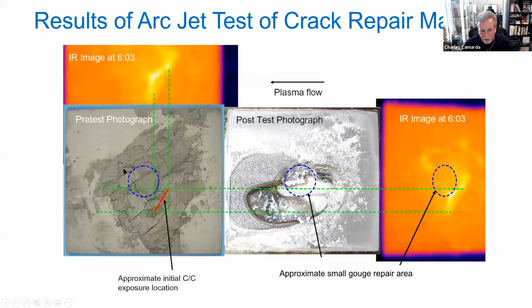specimens, this one had a circular area that was damaged, but you notice that the material that we used, that NOAX material, was slightly too thick, right? And it cracked. And so now when we put it into the arc jet and tested it, a piece of this cracked material flaked off. And when that material flaked off, it caused a step to the flow, right? And that step flow caused this increased heating that you see here. And so now we think this was repaired, but we see that it actually caused additional heating and it actually caused the hole to grow.